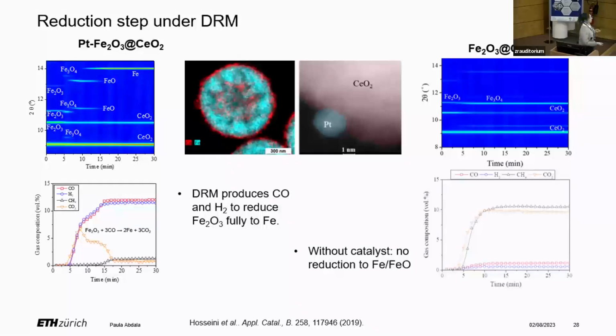To further confirm this, we produced a similar material without the addition of platinum. And we did exactly the same experiment, and here you can see that we only go down to Fe3O4. We are not able to reduce the iron oxide core in the dry reforming of methane, and actually this is also seen here in the gas phase. So we need the catalyst, and this platinum on ceria was very efficient for our purpose.